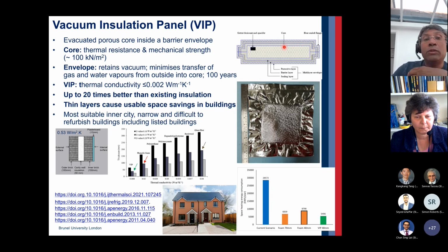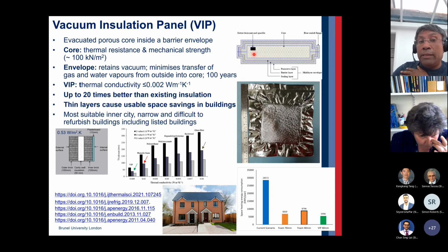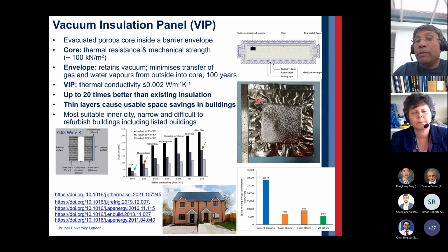Of course, there are other challenges within it, which are listed in our publications shown here. But the benefit, if you can maintain the vacuum and the structure of the VIPs over 100 years, let's say, is that the thermal conductivity of these systems is as low as 2 milliwatt per meter Kelvin, which is 20 times lower than any existing insulation. And one of the insulations that we've developed in our own lab is shown here, which is a rectangular insulation, 150 millimeter by 150 millimeter. But of course, it can be produced in larger quantities and larger sizes as well.